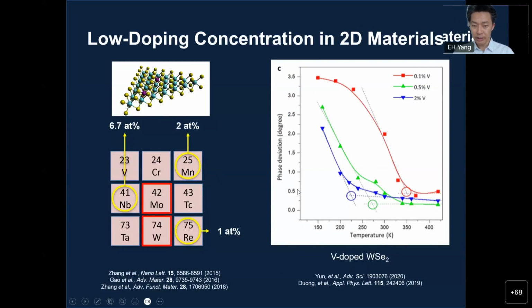But interestingly, in this graph on the right, the y-axis is phase deviation, the x-axis is temperature. So you get some phase deviation. That means you get some ferromagnetic property, and you get a better result when you have lower doping concentration. See, 0.1% vanadium gives a better result. It gets a higher Curie temperature here on the right. This is because when you have higher doping concentration, you distort your lattice, which disrupts this magnetic property, and so on and so forth.